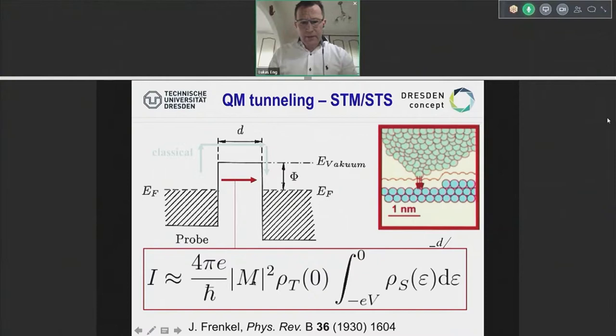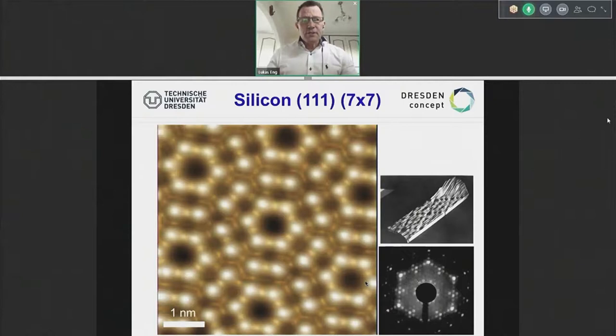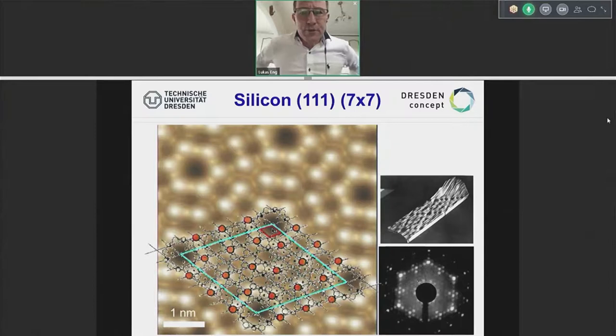But let's take this and look at an example in microscopy, which is one of the most famous examples of very local imaging: the 7x7 silicon reconstruction, where we can see these kind of holes, 1, 2, 3, and 4, which, if you just make a cartoon, show a superstructure of the silicon, where within this 7 by 7 atoms, which is 49, we have exactly only 12 atoms. These atoms have different chemistry, a completely different work function than the bulk has. In other words, the system self-organizes itself into these two triangles, 6 here and another 6 here.